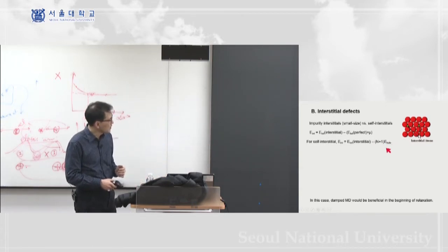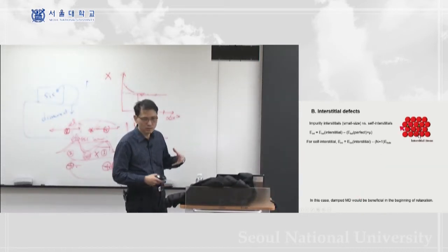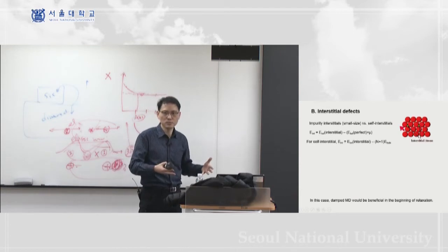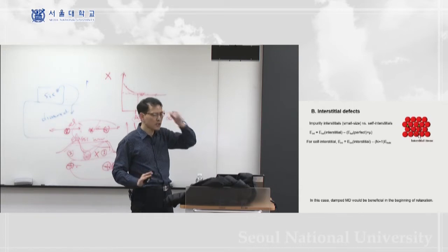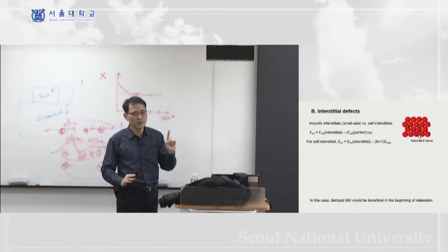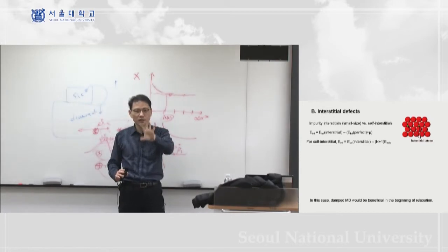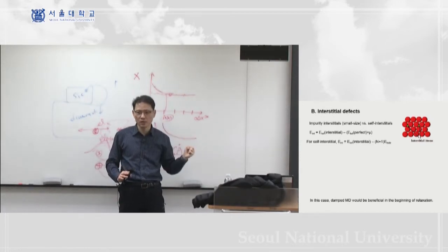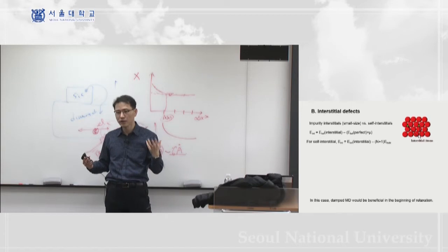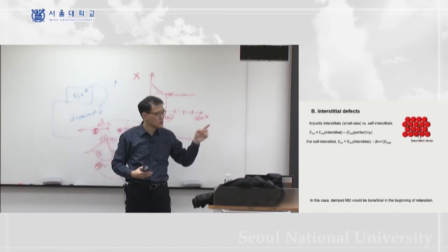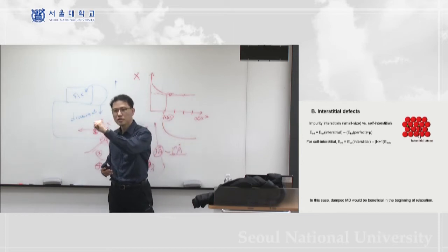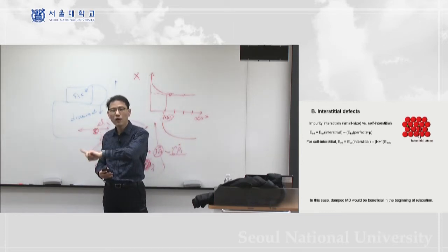One tip is that since the interstitial causes a larger relaxation around the defect site, because it gets into the space and pushes out atoms quite significantly, in many cases we first start from some initial guess. In the case of the vacancy, you simply remove the atom, which is a very good starting point, and the atoms relax afterward. In the case of interstitial, you have to put atoms at a specific position, and it requires your guess of the initial position.